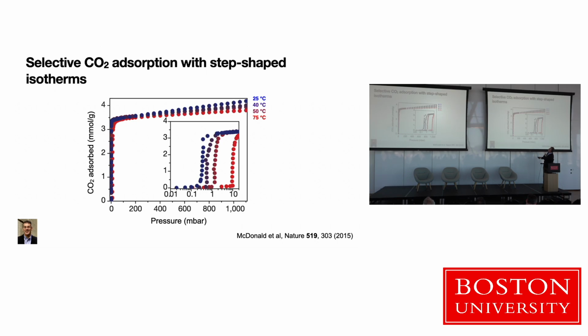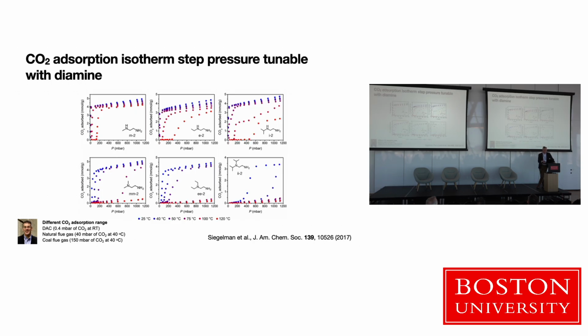So this is adsorption versus pressure. You imagine turning up the pressure of your gas, and once you hit a threshold, you go from empty MOF to full MOF. It's like a diode. And that's not Langmuir-like, and that is a direct result of this cooperative behavior. Now this threshold can be tuned with temperature and pressure, but it also can be tuned chemically with the ligands. This is just different amines, diamines that have different appendages and structure,